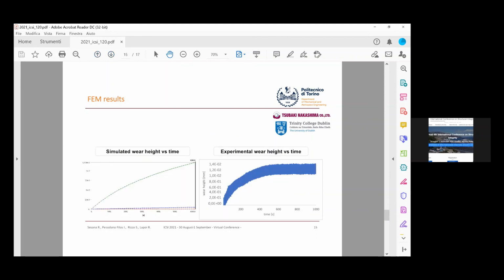The experimental and simulated wear rate over time is reported in this slide. What we can see is that the trend is very similar, therefore the adopted procedure works also in the case where the material is not homogeneous, like in our coatings.